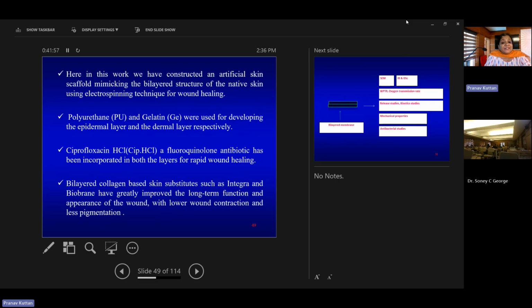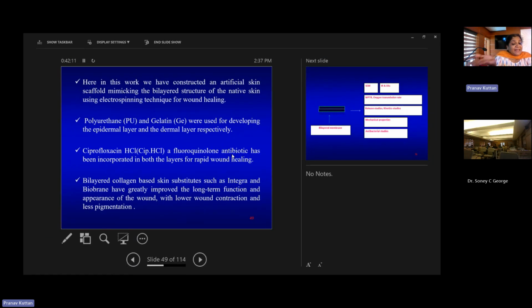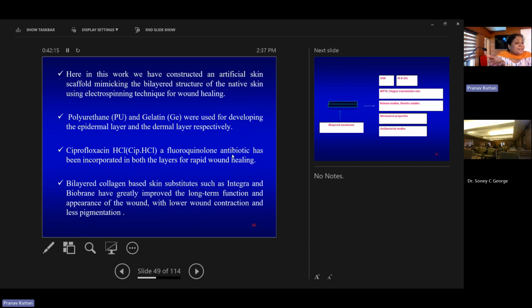So here in this work, we have constructed an artificial skin scaffold mimicking the bilayered structure of the native skin using the electrospinning technique. Polyurethane was used for developing the epidermal, that is the outside layer, and gelatin was used for developing the inner layer. The reason for choosing polyurethane was that the outer layer has to provide protection against bacteria, etc. So we used a synthetic polymer for that outer layer, and gelatin was used for the inner layer because gelatin is of biological origin. It resembles human tissue very closely. That is the reason why we chose gelatin.